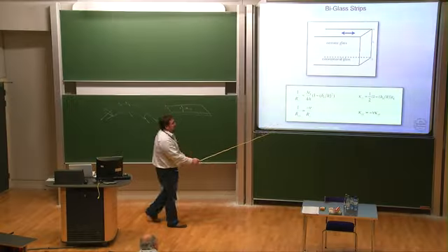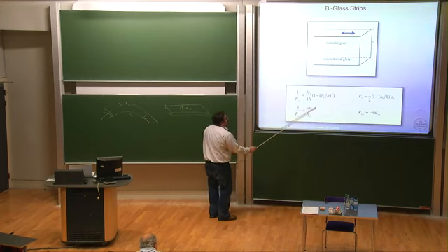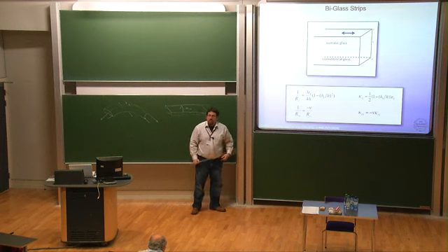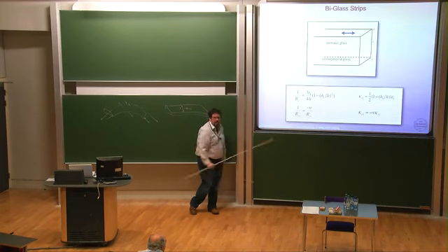And again, you just turn the crank on the strains and you get curvatures out. Now we're in this sort of intermediate regime. H1 is the height at which the bonding occurs relative to the total thickness of the material. So here, in this intermediate regime, you get strong bending one way and the Poisson amount of anticlastic bending the other way. So this now looks exactly like traditional bending, where you have some imposed amount of bending and you get, to first order, a suppressed, Poisson-mediated curvature the other way.